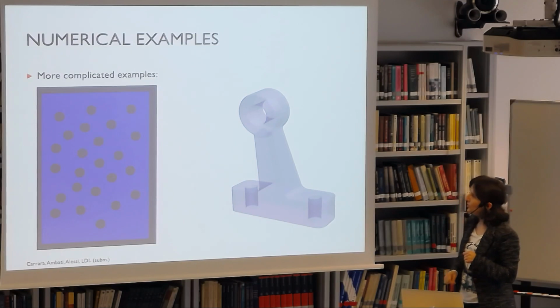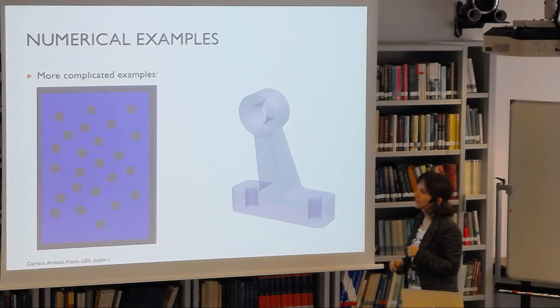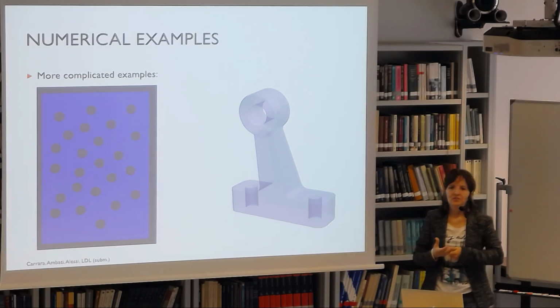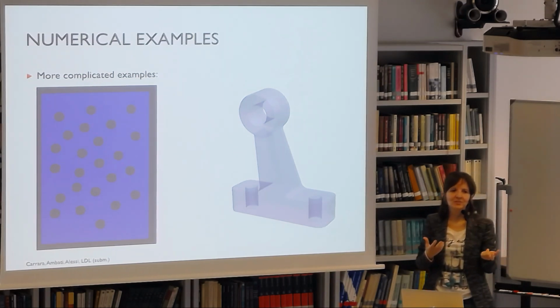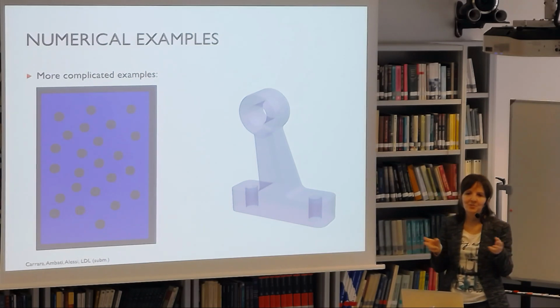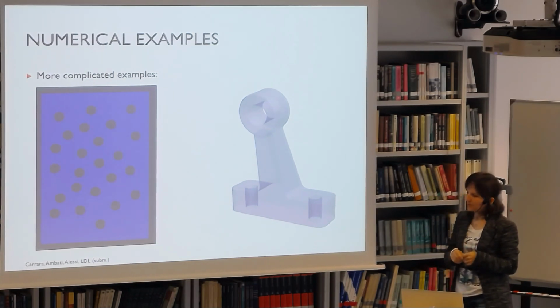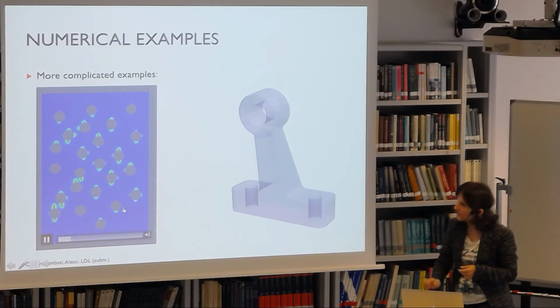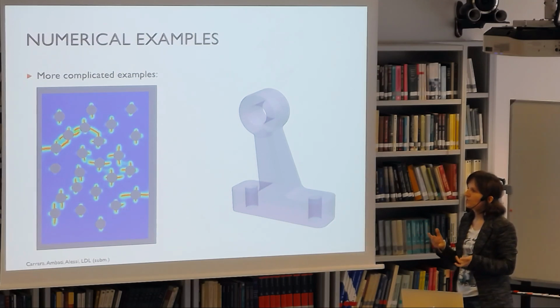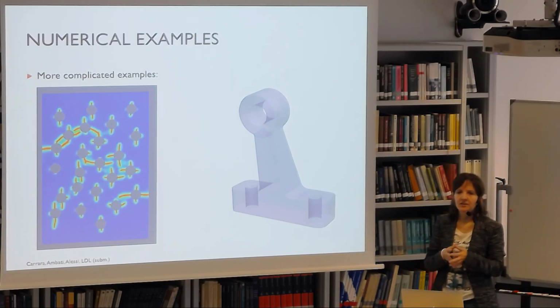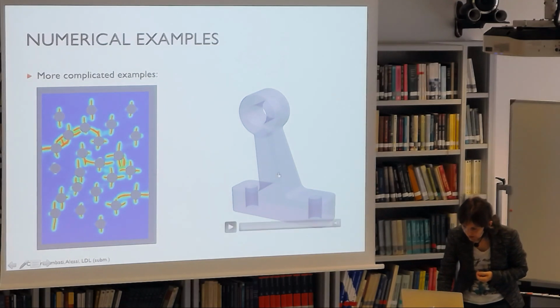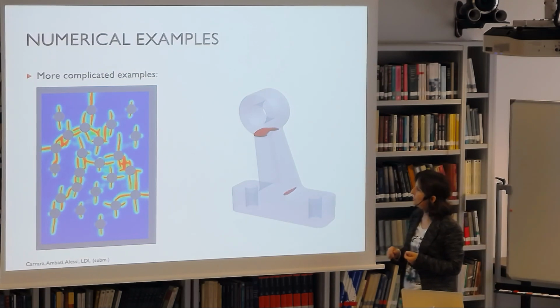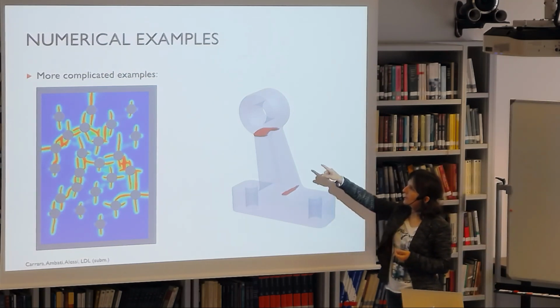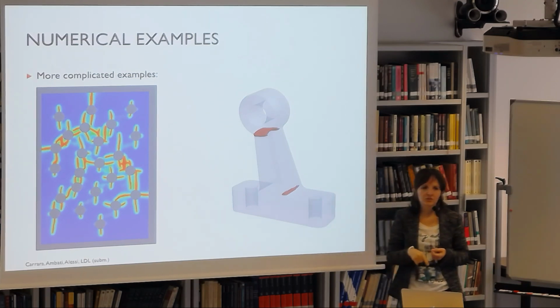Now, to conclude, I just would like to show you that the beauty of this approach is that you can not only analyze compact tension specimens. This is something that you could do also with the standard approaches available already, but with the phase field approach, due to its flexibility, you can analyze, for instance, fatigue in complicated geometries where you have multiple cracks intersecting and branching, and also you can analyze, for instance, in this case, a 3D machine piece where you have fatigue effects that start in one part and then continue in another part.